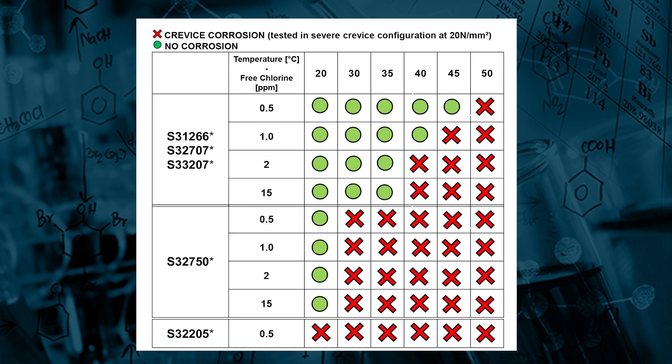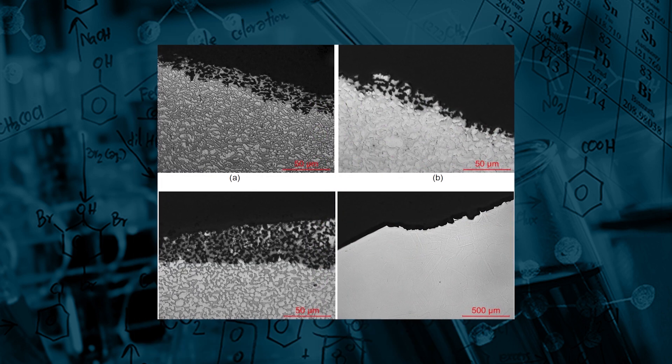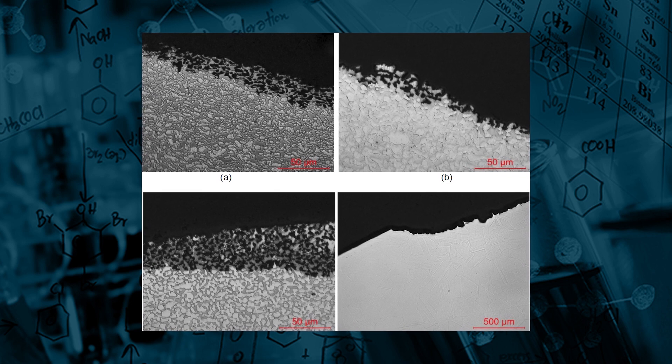Another very nice contribution of this article was to present the microstructure of selected corroded specimens in the different environments. Selective dissolution of the ferrite phase was observed for some specimens in the model tube heat exchanger, while in the crevice environment, the austenitic phase was selectively corroded.